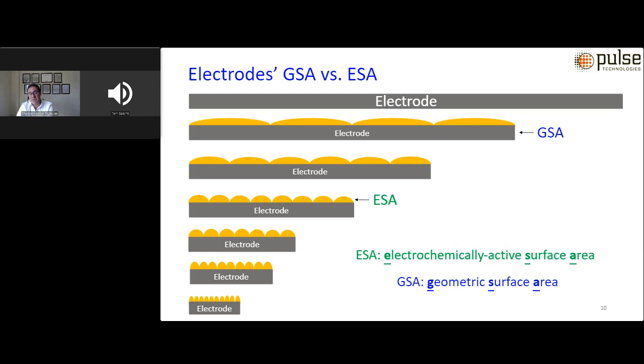To overcome this trade-off, an alternative approach is to increase the number of electrodes to achieve high selectivity or, for example, flexibility in the device, where each electrode has a smaller geometric surface area, but with enhanced electrochemical surface area, and that can be achieved by technologies such as coatings and certain surface treatment technologies that could be applied on the surface.